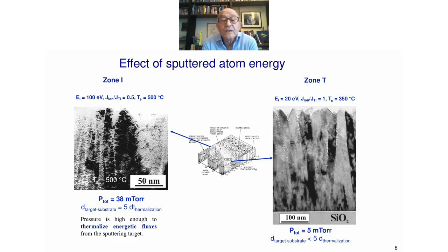Going down to 5 millitorr, this is an example of making use of the energy of the sputtered species. The films become dense with small grain size, but then competitive growth occurs, and eventually they become rough with open grain boundaries.